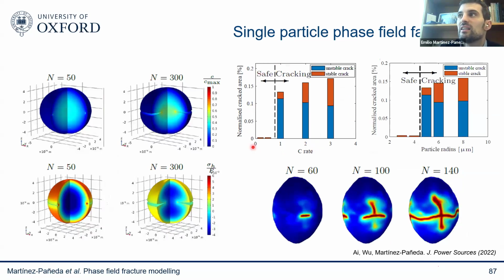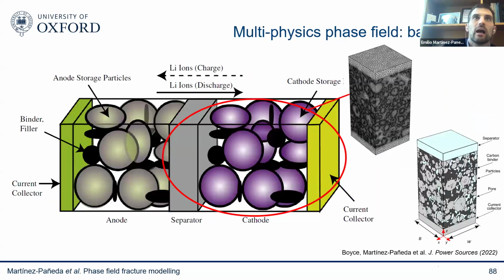We can change the C rate and see what operation conditions are safe. We can also change the particle size, for example, and tell industry what the ideal particle size is that they should be looking into to prevent those cracks from forming. And not only can we do simulations at the particle level, but we can also do simulations at the electrode